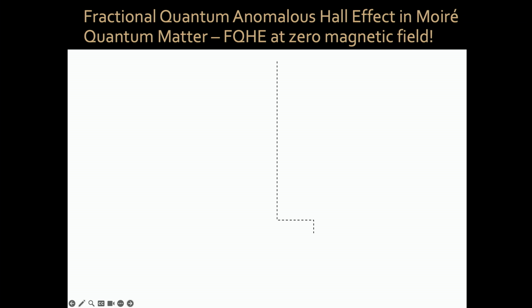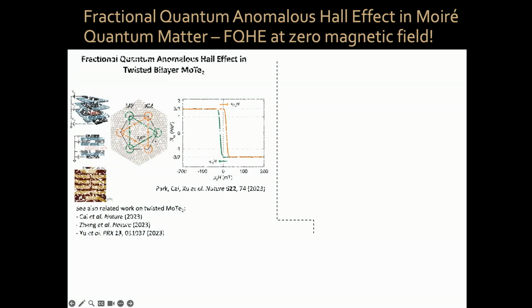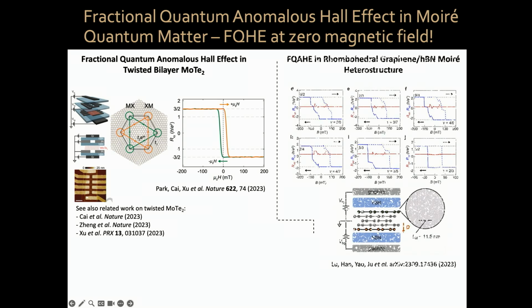The first group was the group of Xiaodong Xu, and then also several other groups worked closely after, where they realized this not in a graphene-based system, but in a transition metal dichalcogenide system, twisted bilayer molybdenum ditelluride. Here you can see a fractional number, 3/2 in resistance, which means 2/3 in conductance, happening at zero magnetic field. Yeah? And a little bit later, my colleague Long Ju at MIT realized the fractional quantum anomalous Hall effect in complex systems called pentalayer rhombohedral graphene aligned to HBN. It's an interesting Moiré heterostructure between hexagonal boron nitride and a 5-layer graphene of a special stacking.